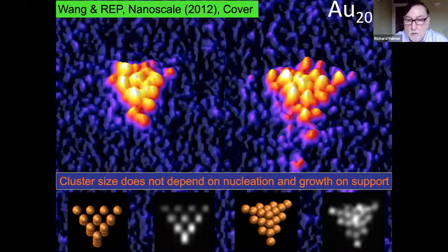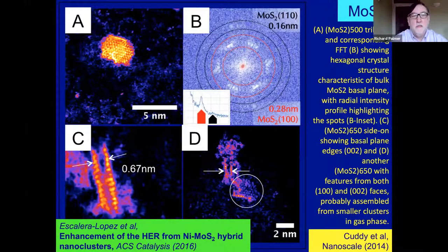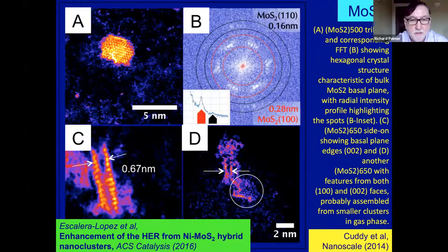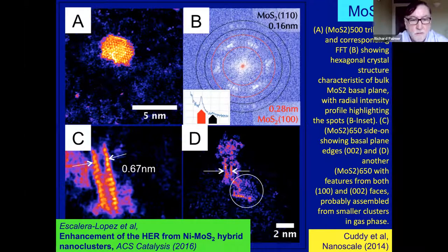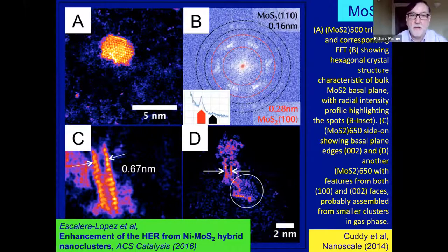We do not just make elemental particles. This is a two-layer nanoparticle of a layer material, molybdenum disulfide — a platinum replacement candidate, though that is a difficult challenge. This is a nickel-doped molybdenum disulfide with three different chemical elements in the nanoparticle, used quite successfully for enhancing the hydrogen evolution reaction in electrocatalysis. If you have a more complex target or targets, you can make more complex nanoparticles before you size- or mass-select them.